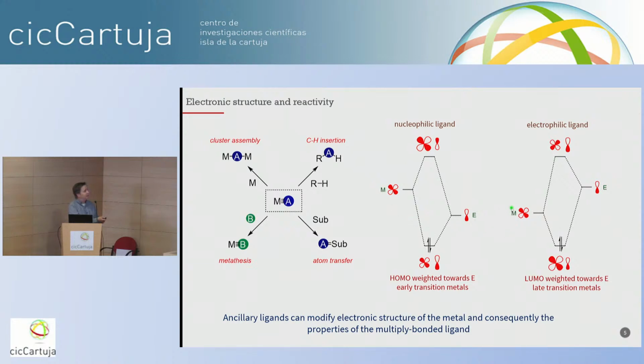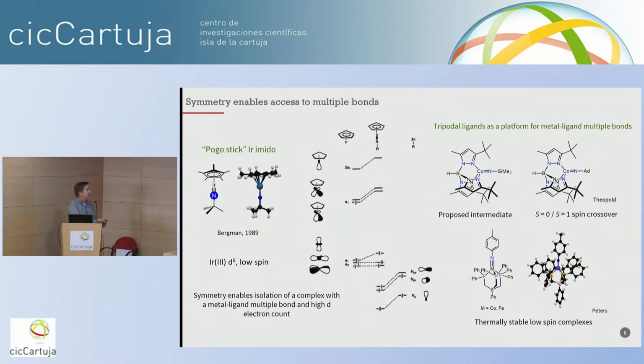Conversely, if you have a later metal, or you lower the energy of the metal-based orbitals, then the LUMO is now weighted towards the elemental ligand, and this should be more electrophilic in character. So there's opportunity here to change the nature of the reactivity. Okay, so if we can't easily make a compound that has a 6-coordinate metal ligand multiple bond, because we're going to populate metal ligand antibonding orbitals, how do we get around this?